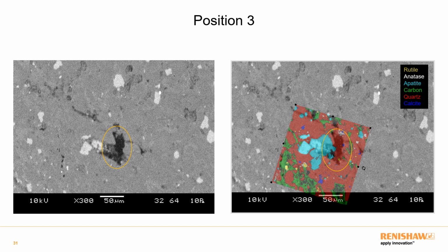The other thing I want to highlight from this image, which is important when looking at any of these combined techniques, is that we need to be really careful because we're not really comparing apples and apples. This is more an apples and pears situation. You can see we've got a very nice match with this region of apatite, but in the Raman image, the apatite seems to extend outwards to the right-hand side, and that's not shown in the SEM image. That's because the Raman and the SEM measure at very slightly different depths from the sample. In this case, we've probably got a situation where the SEM is more surface sensitive than the Raman measurement, and it's likely that we've got an apatite region moving slightly below the plane as we go to the right. So we pick it up on the Raman, but we don't pick it up on the SEM.